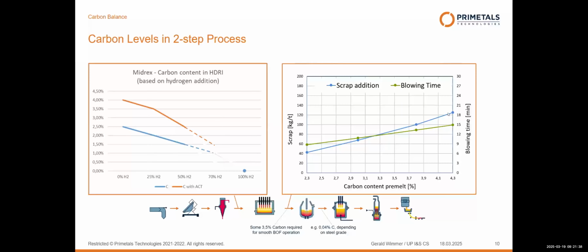For all plants that go into a transition phase, having blast furnace and smelter operated in parallel, this is, of course, a classical example where a powerful process model on the BOF converter makes sense, so that you really go heat by heat, depending on the raw material you get, either from the blast furnace, saturated in carbon, or from the smelter, lower in carbon, or a mixture of it. You can precisely calculate the amount of scrap that can be charged to achieve the tapping temperature.